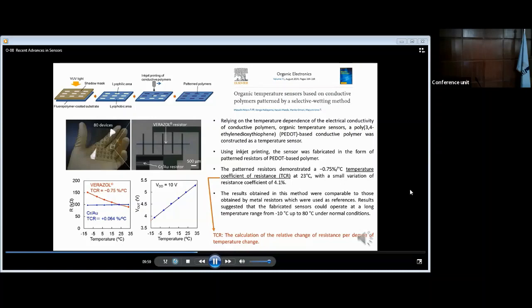The technology used here is called inkjet printing, and the sensor was fabricated in the form of patterned resistors of PEDOT-based polymer. These resistors demonstrated minus 0.75% per degree Celsius temperature coefficient of resistance at 23 degrees Celsius, and the temperature coefficient of resistance, as shown down here, is the calculation of the relative change of resistance per degree of temperature change.